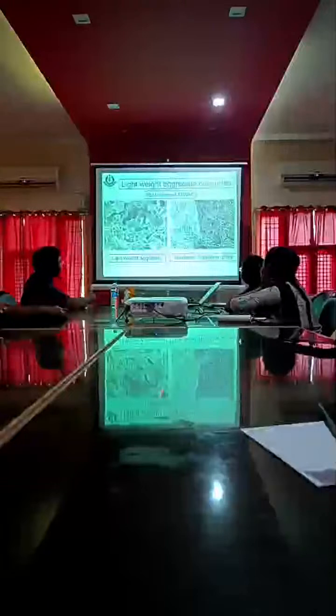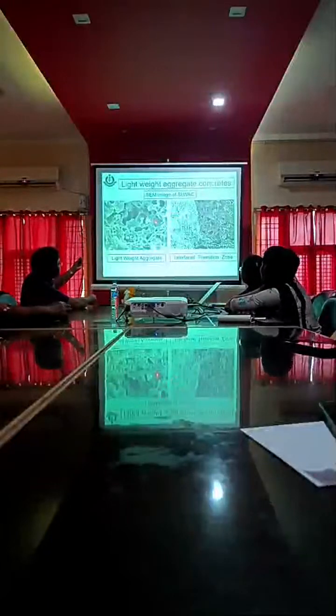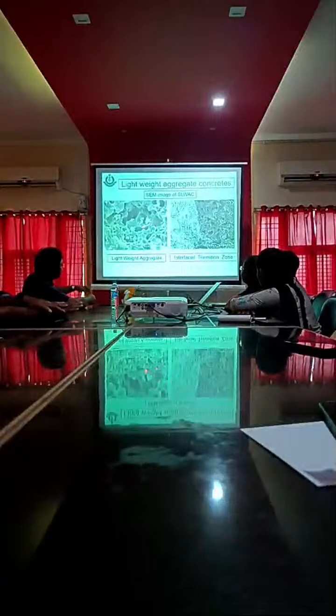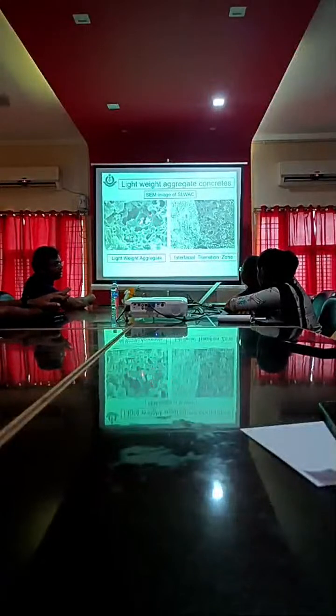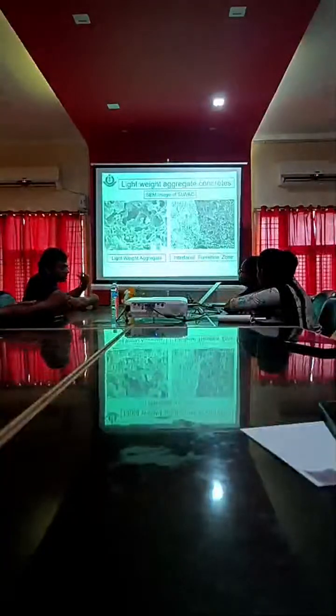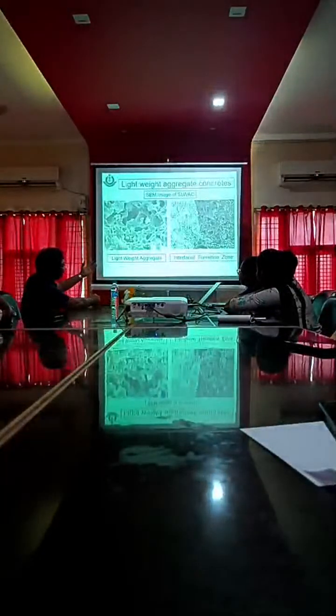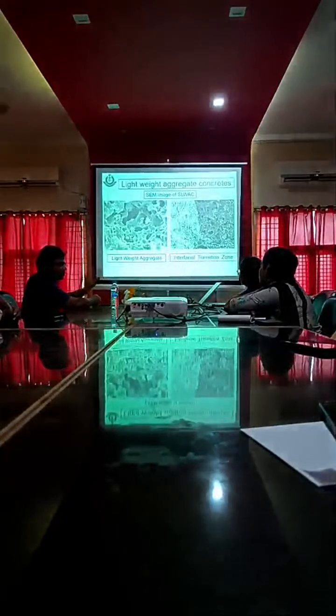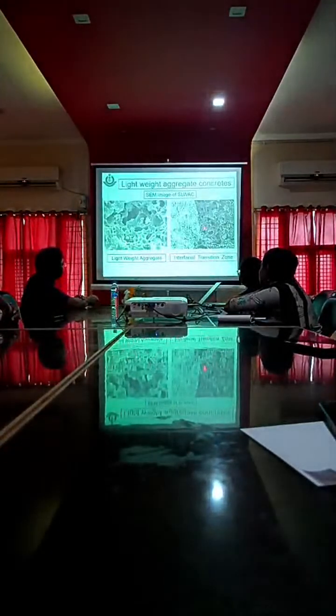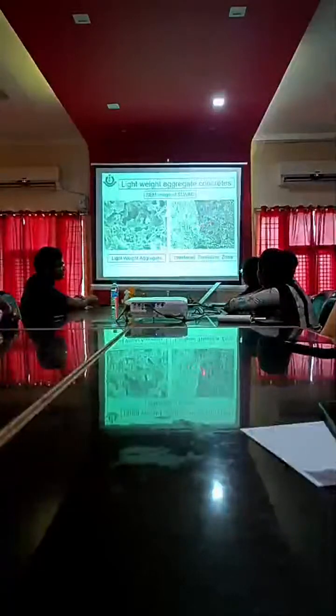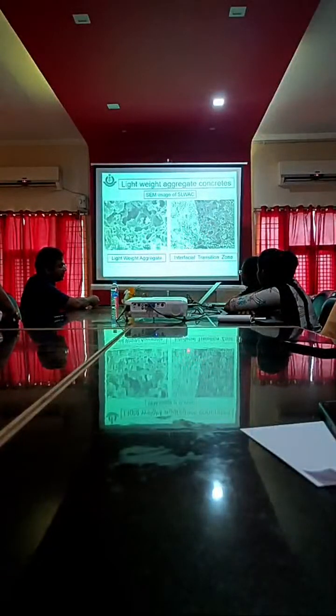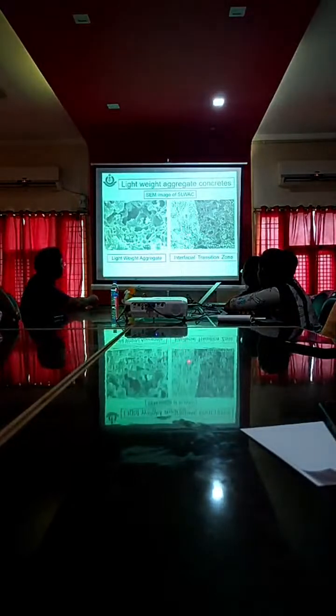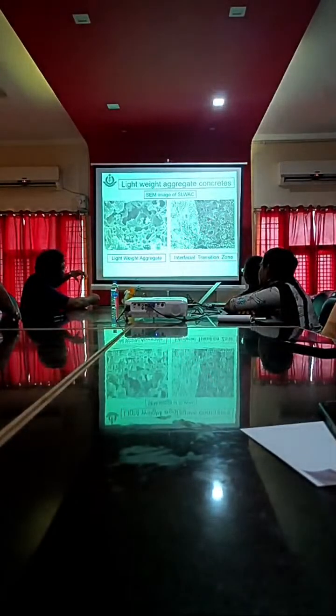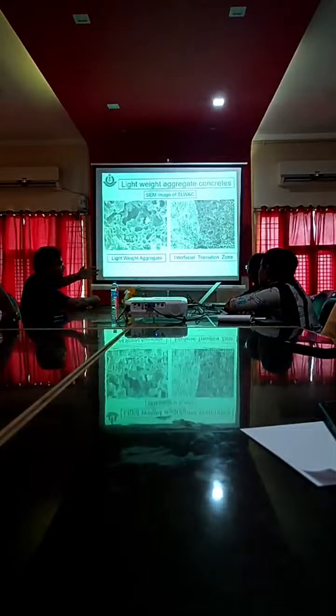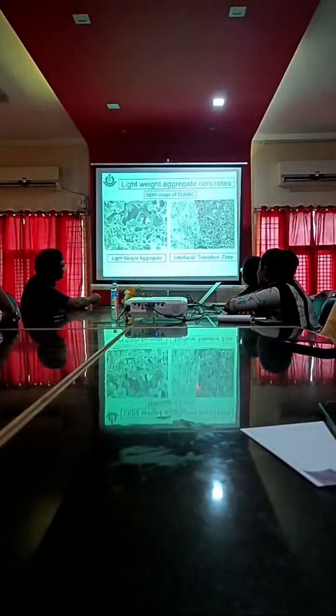You see this, you take an SEM image of a porous aggregate, a single aggregate, see the microscope, you see a lot of pores are there. It's a porous material. Because of this porous nature, there is a lot of water absorption, nearly 20%. But the conventional aggregate has about 1% absorption. This is what happened and this is the interface. What is the interface transition zone here? Any idea about this? Yes, it is a zone between the aggregate particle and the mortar particle. You consider it as a weak zone. Okay, that zone will be densified.